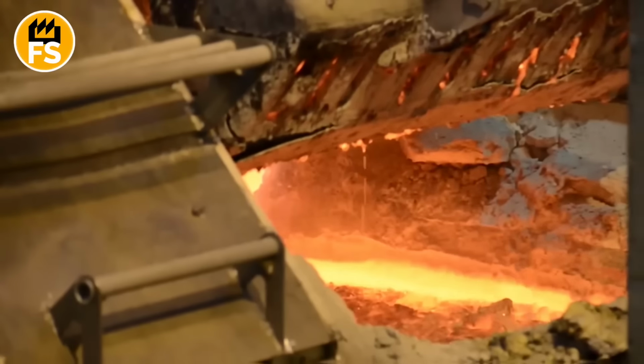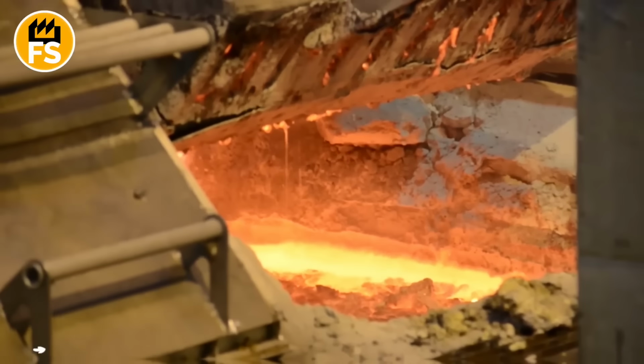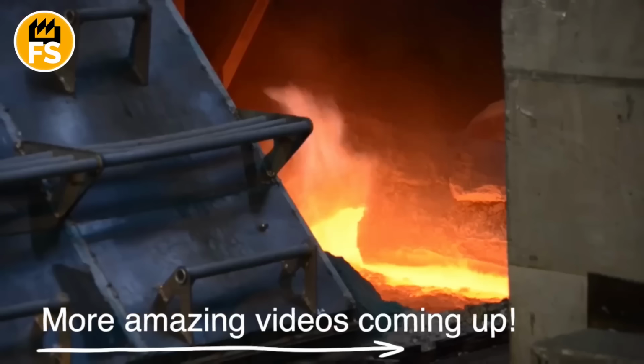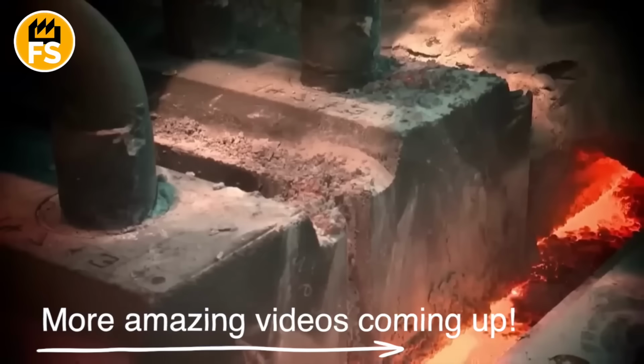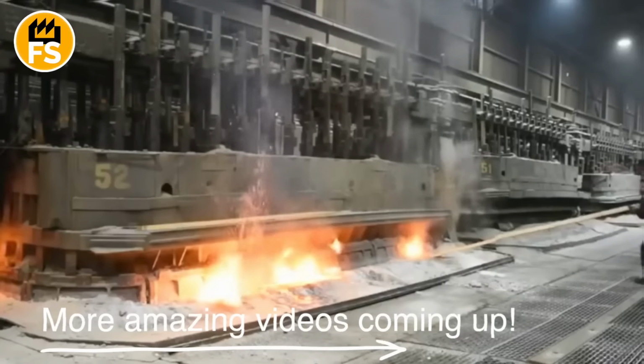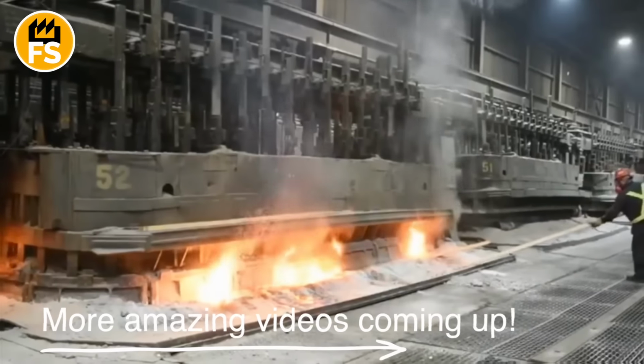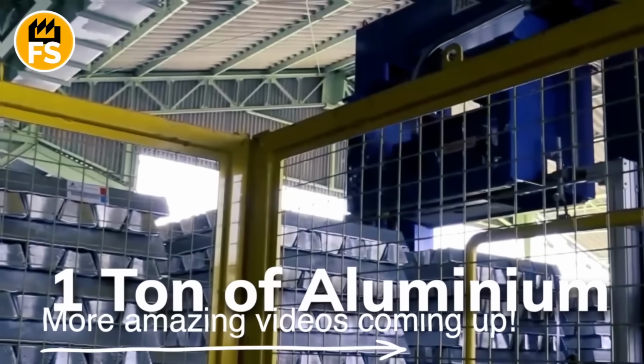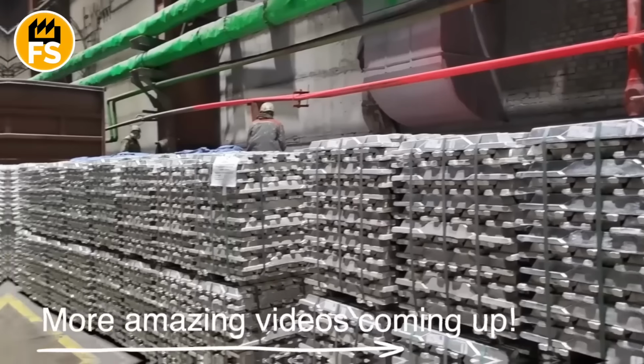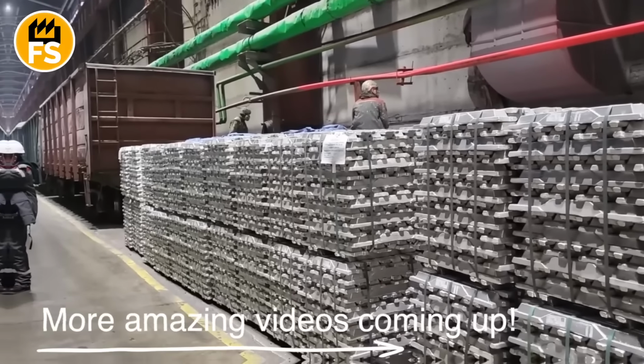A massive electric current, tens to hundreds of thousands of amps, runs through the molten mixture. Oxygen gets released at the anode and burns off, while pure aluminum settles at the bottom of the bath. Producing 1 ton of aluminum consumes roughly 15,000 kilowatt-hours of electricity. That's about what an average apartment uses in a year.